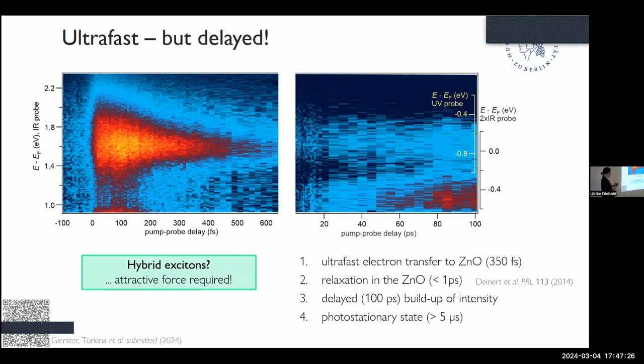And when we talk about scenarios of why charge separation doesn't happen in zinc oxide as efficiently, the trap states, the polarons are very often discussed. And while we cannot exclude defects and polarons as potential traps at such interfaces, we can exclude that this reoccurring signal is coming from defects and polarons, because defects and polarons do have attractive potentials possibly at the surface, but this wouldn't depend on the excitation mechanism.